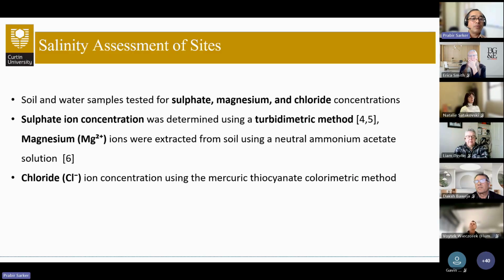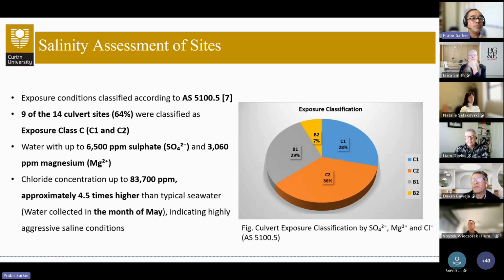Soil and water samples were also tested for sulfate, magnesium, and chloride contents in the chem center. The results were used to classify the exposure condition according to AS 5100.5, and it was found that 9 out of the 14 culvert sites were classified as exposure class C, which is C1 and C2, as shown on the right hand side diagram.